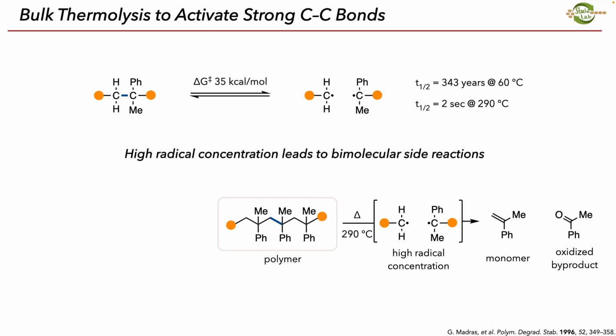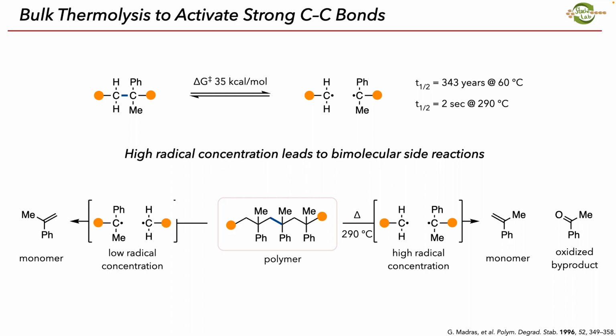And so we have our polymer, we heat it up to 290, we generate this high radical concentration because it only has a half-life of 2 seconds, so you're going to break a lot of those carbon-carbon bonds, but in doing so, you can generate monomer. You're also going to have side reactions because you have so many radicals which are highly reactive. These can react with oxygen, they can react with themselves to reform that bond, or they can react with a different one, which will give you a new compound. So we can definitely generate monomer in this process. We're also going to get a lot of side reactions, which is not a selective monomer stream.